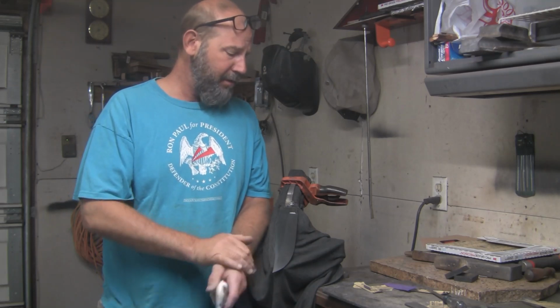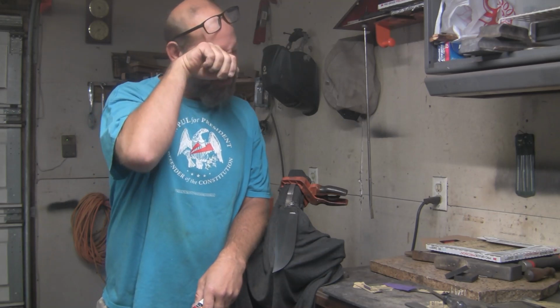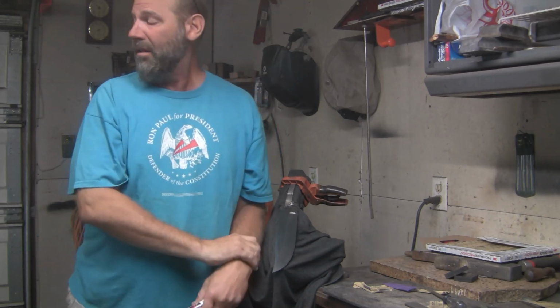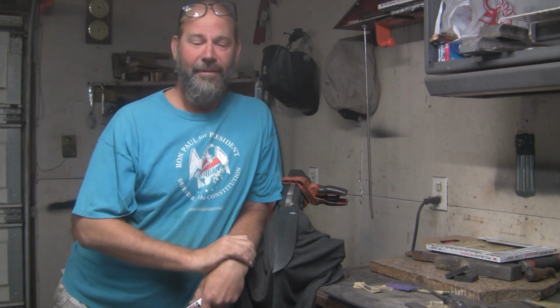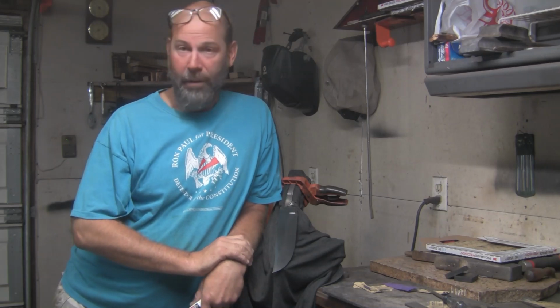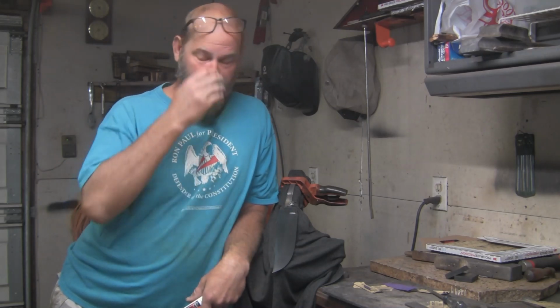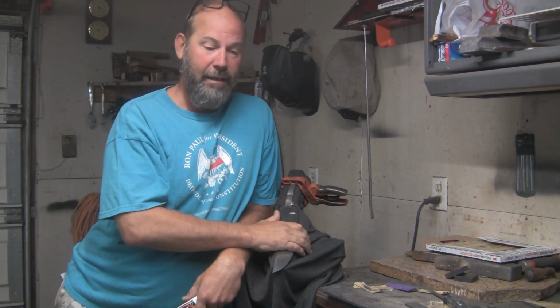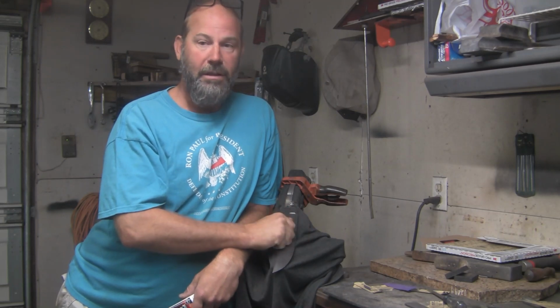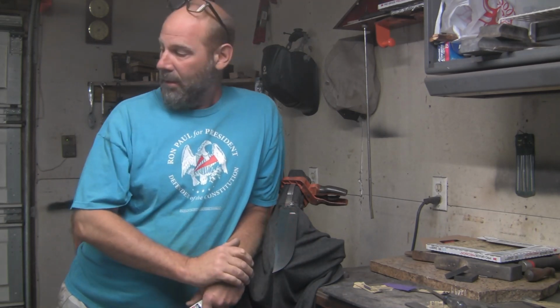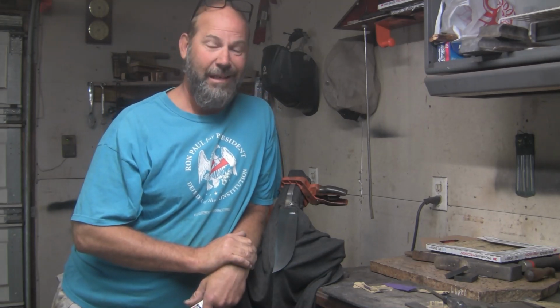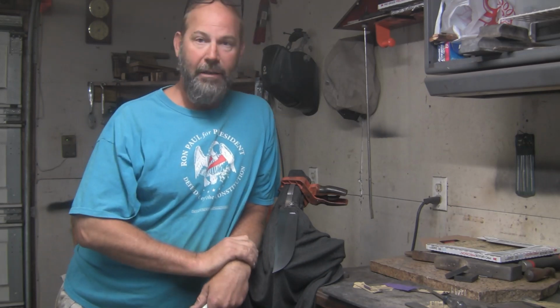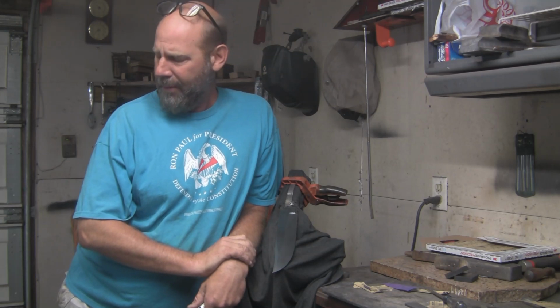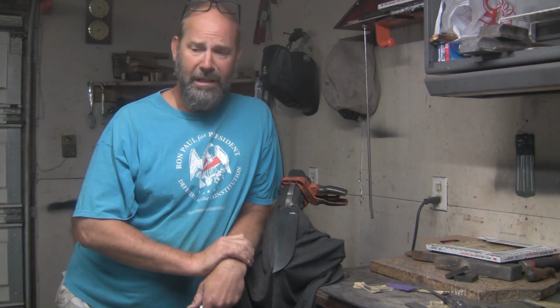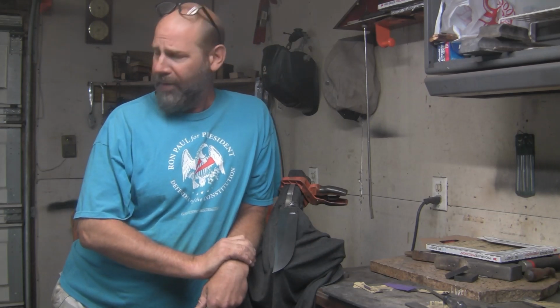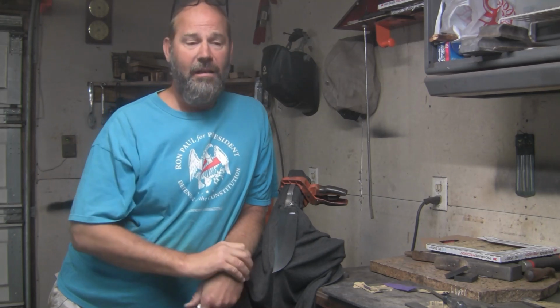Yeah, so I'm going to go ahead and get started here. This is a 1070 steel. I've already tested this steel, tried to oil harden it in the oil that I have, and it did not harden very well. It did water harden though, so what I'm thinking about doing is putting the clay on, get all that set up, and then when I go to do my quench to harden the steel, I'm going to do a double quench. I'm going to go into water for a second or two, and then straight into preheated oil. I'm going to try to heat the oil up pretty hot, probably up to around 250 degrees, 300 degrees, get it as thin as I can, and hopefully from there that won't cause any issues.